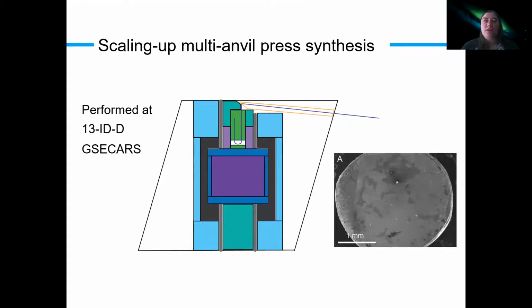Since we saw that this material forms very readily after you reach the lead melt, one of the things that I did was put in a slight excess of lead in order to do a flux growth for this material. And what a flux growth means, for those of you who don't know, is that you are using the liquid metal as your solvent. And so we're doing this at high pressure, using the liquid metal as our solvent. And since we're no longer running X-rays through this cell, we can scale up the sample to on the order of a couple millimeters.